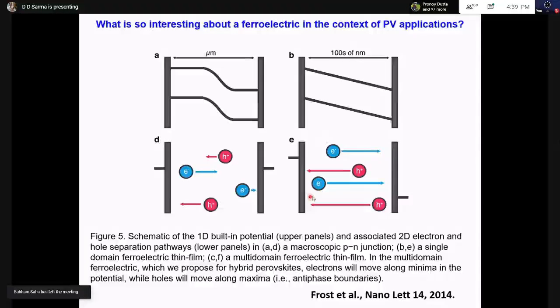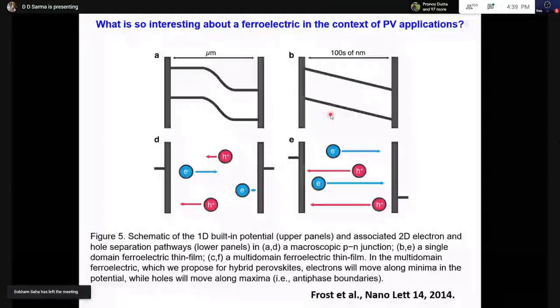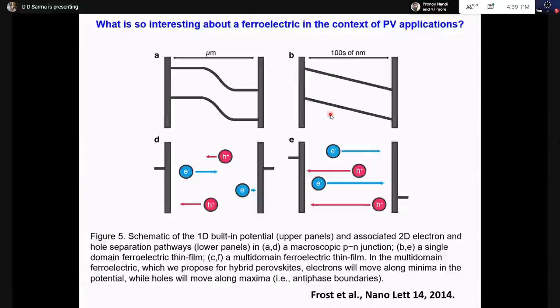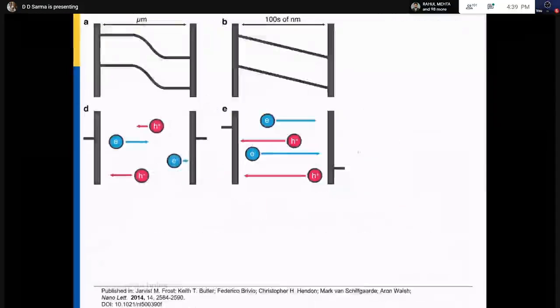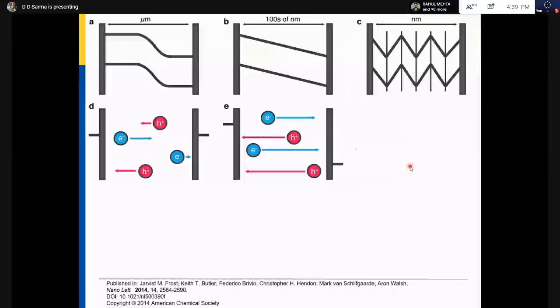But here is a chance. This material has a band gap of 1.55 electron volts. And it has dipoles inside. Can it be ferroelectric? In fact, the actual thing is a bit more complicated because you don't make a single domain device. Your material will be thick enough, not a single domain. So ferroelectric domains will be pointing in all different directions so that it will not drive your system all the way to the electrode. The electron will not go all the way there.